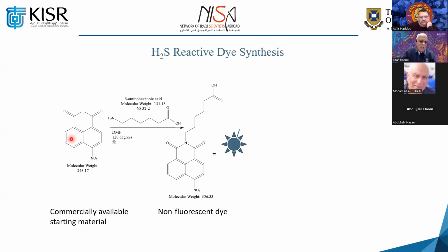We started with this type of molecule. It is a commercially available starting material. Then, of course, we reacted it with 6-aminohexanoic acid, a reaction through the amine group here. Then we were able to produce that compound. And this compound, of course, has a nitro group. It is not emitting. It is not fluorescent. And this is what I'm going to designate with that symbol for all this type of material. It's a dye, a non-fluorescent dye.